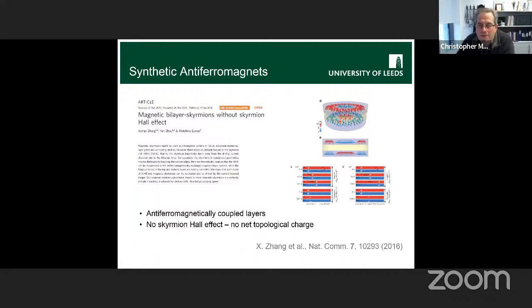And what that means is, well, the Skyrmion Hall effect should go away, but there are also predictions that these Skyrmions should be faster to move, and can be smaller as well. So we thought this was an interesting thing to look at. And then COVID happened.